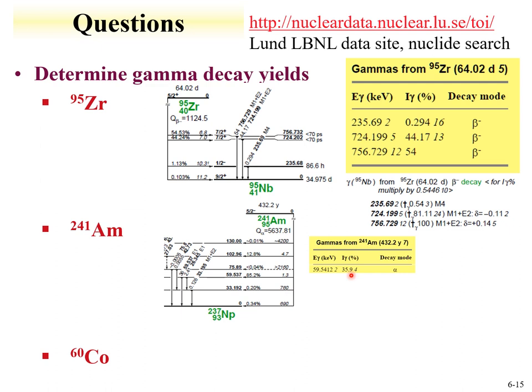And the reason for that is, even though it occupies this same energy level 85% of the time, it has two routes for de-excitation. 36% of the time, so that agrees with this value, it decays from this 59.5 keV excited state directly to the ground state. That would yield this photon. And then another percentage of the time is listed here. You see it goes from this 59.5 keV energy state to a 33 keV energy state, and then from that 33 keV energy state to the ground state. So there's these competing transitions.